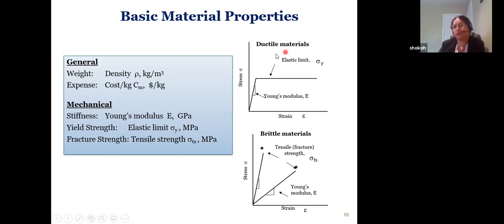For ductile material, which has elasticity, these two can be shown here. In the linear deformation, the stress over the strain gives the tangent, which gives me the Young's modulus, and then I get an elastic limit. This elastic limit is the representation of yield stress for ductile material. For brittle material, I'm focusing on fracture strength, because I don't get a yield and don't get much deformation. So I use that curve to find out how much strength I have to reach fracture. For the second material, I get a lower modulus but it is tough: the area under this curve is much bigger than this one.